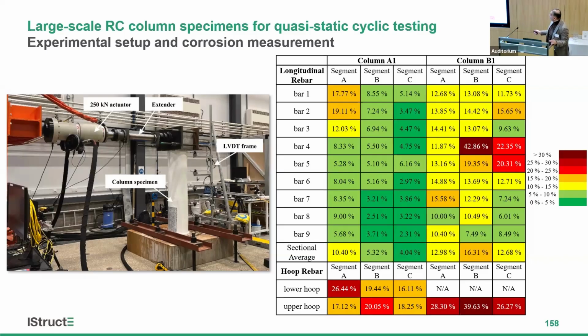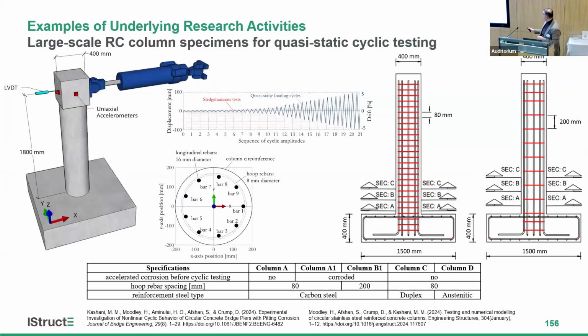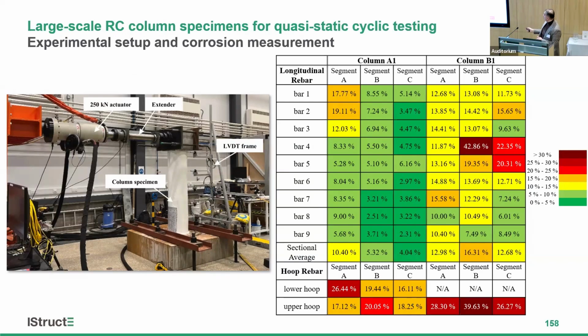And this is the result. After we tested the columns, we demolished them and took the reinforcement out. If I refer back to this figure, sections A, B, C are essentially 3 segments, each of 200 millimeters. We demolish and measure the mass loss of every individual bar. There were 9 bars across the section, and the hoops. So this is essentially a heat map of the mass loss percentage of the corrosion.